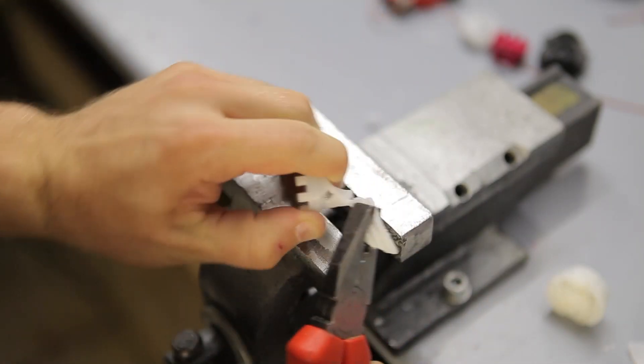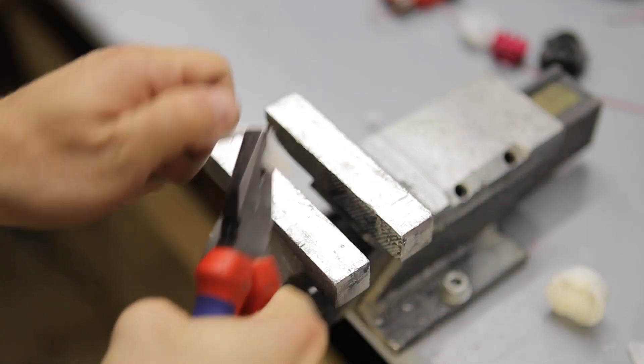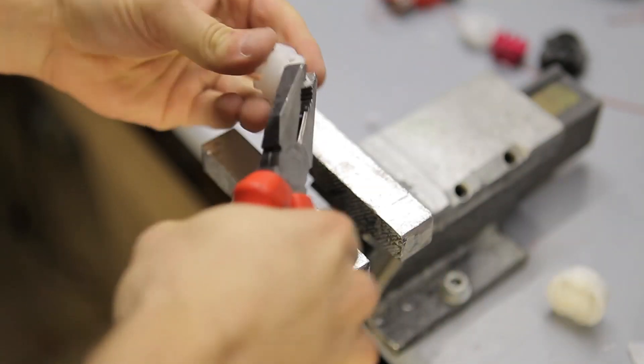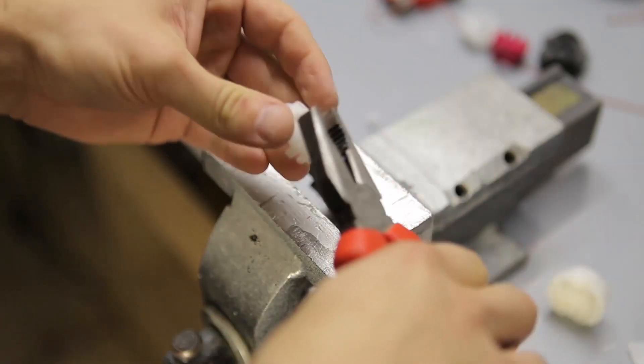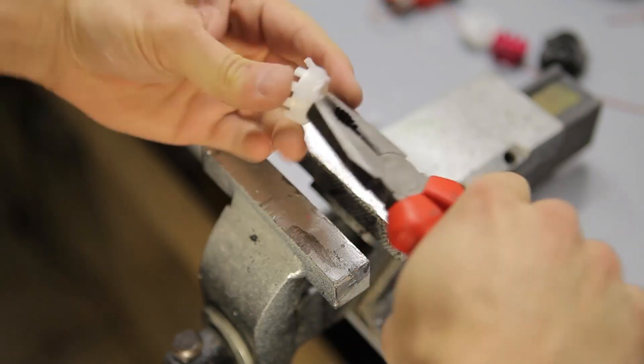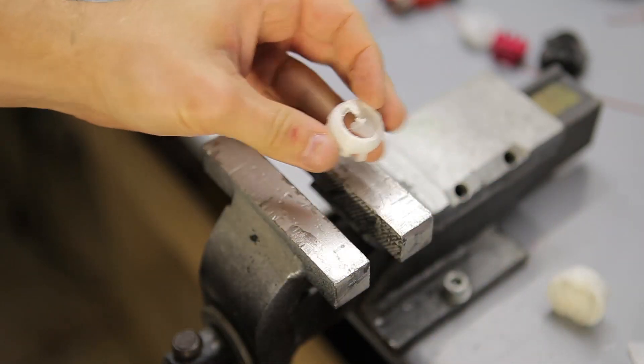Now, the Taulman nylon actually was a very solid performer. It is not as stiff as PLA, ABS or the Formlabs SLA part, but it does have an overall very nice layer bonding strength and the material itself also fails very gracefully.